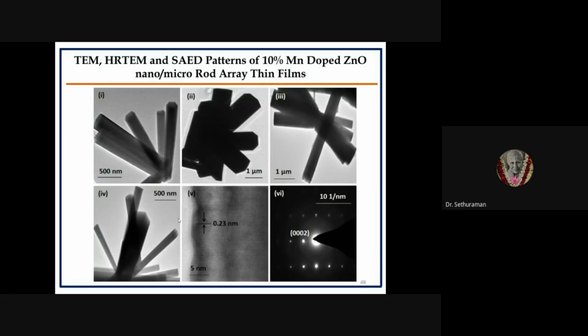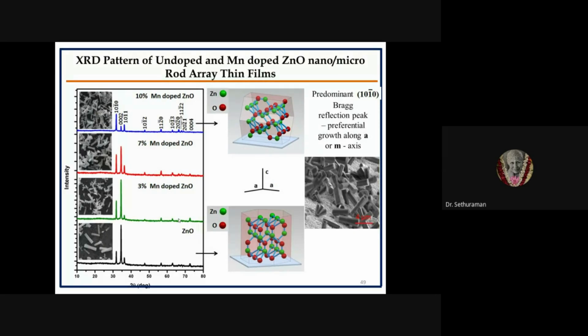This is the 10% sample. Here we found almost only micro rods in the HRTEM. We also found the crystallographic orientation for 10% and 20%, and the lattice spacing we have calculated from the HRTEM images. These are the XRD patterns of the doped and undoped samples. You see this one is undoped zinc oxide, then 3% doped, and then 10%. You see the change of orientation. For 3% and 7% the dominant orientation is (0002), but after increasing the doping percentage, that orientation is demolished, and we found the (10-10) orientation of the micro rod assembly of zinc oxide.